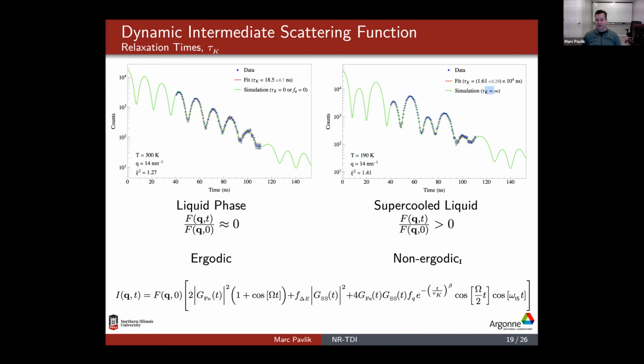Again, the blue is the data points. So in this case, the non-ergodicity term is adding a fractional portion of this, giving us a fraction of this instead of eliminating it. And we can see again, this goes back to what we saw in the forward direction with just the foils, the high to low, high to low. We can measure the relaxation times by analyzing the depth of the troughs and peaks between these 2 graphs.